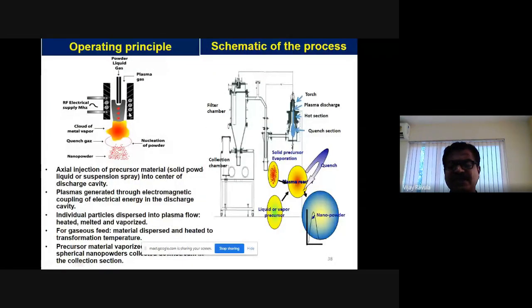So typically, as I was mentioning, a powder comes into the plasma zone. Then it becomes vapor, and then the vapor is quenched with a quench gas. So rapid solidification takes place. Once they start nucleating as a solid, they are all pushed away by the gas, so they don't stay. If they stay, then particle growth will happen. So that's why you have the plasma discharge hot section, then you have a quench section,